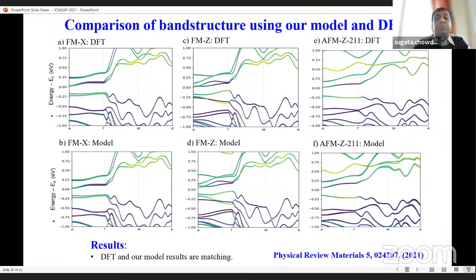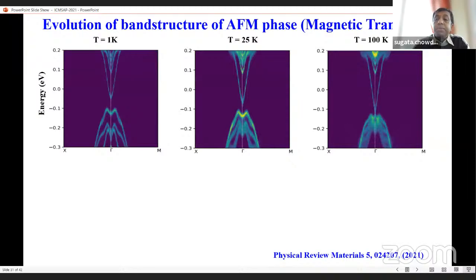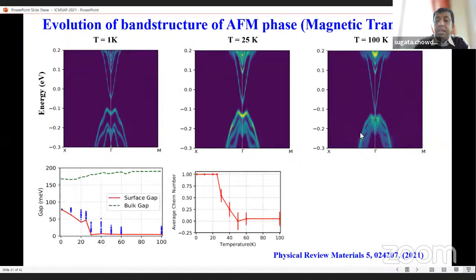So we started looking. What we did, first, we compared the band structure using a tight binding model that we developed. What is the tight binding model? With the DFT, we found that the DFT result and the tight binding model give a similar result. Then, encouraged by this development, we focused on the temperature, how that band gap is changing. And here, this is the prediction using that tight binding model. We found there is a gap. The gap is reducing, and this is at 100 Kelvin.